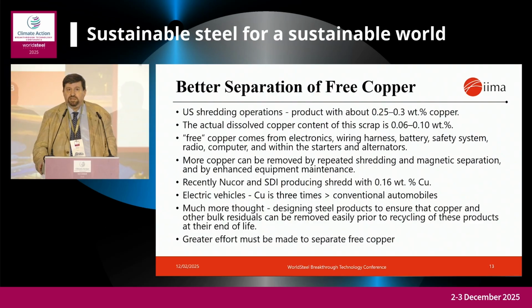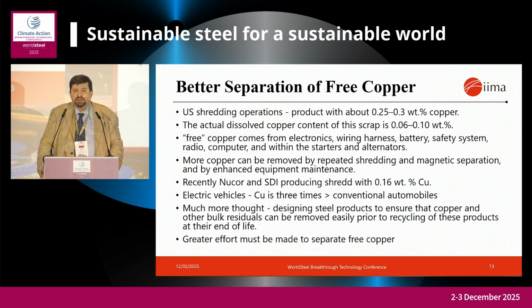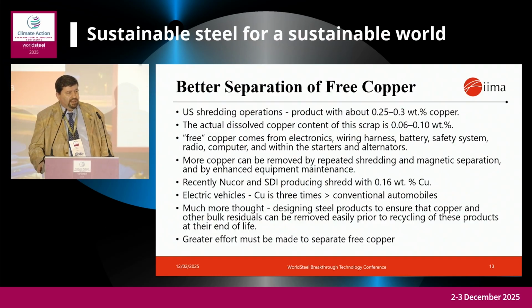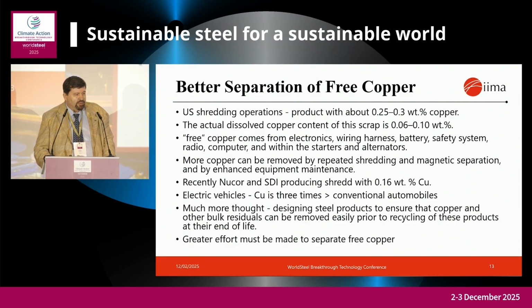Because of the situation in the Ukraine, the availability of merchant pig iron was greatly compromised. So several steel groups in the US began upgrading their shredded scrap, typically taking it from 0.25 to 0.3 weight% copper down to about 0.16. And this reduced their dependence on pig iron. Now, copper can be removed by repeated shredding and magnetic separation, and you can use a process called ballistic shredding that produces very, very small pieces.